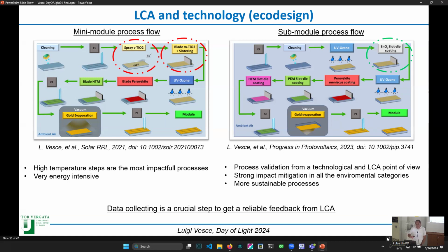And these are two processes. So the high temperature process is something that you have not to do if you want to have a low impact process. So we remove these two processes and we move to a low temperature process for the ETL. But it's also good from a technology point of view, because in the case of big modules, high temperature processes are not good because you can start to fail your devices. You can start to make deformation of the device and so on. So it's good also from this point of view. And in fact, we show the mitigation in all the environmental categories of the process.